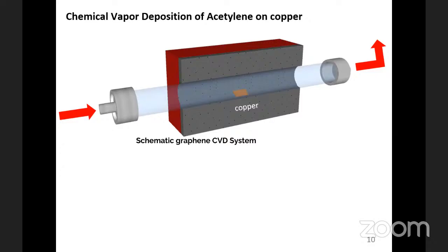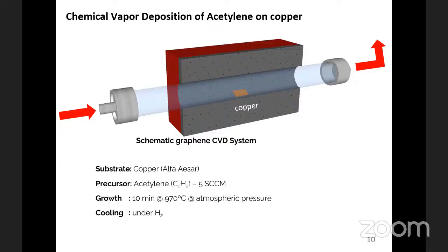This is a schematic diagram of the chemical vapor deposition chamber in my PhD laboratory in India, and I used acetylene as a carbon source for the growth of graphene. When acetylene is introduced into the chamber at 970 degrees Celsius, the copper acts as the substrate, and in fact as a catalyst, for the growth of graphene. A metal catalyst is always needed to induce the growth of carbon-based material. Most people choose copper because it has a very low carbon solubility that results in monolayer growth of graphene.